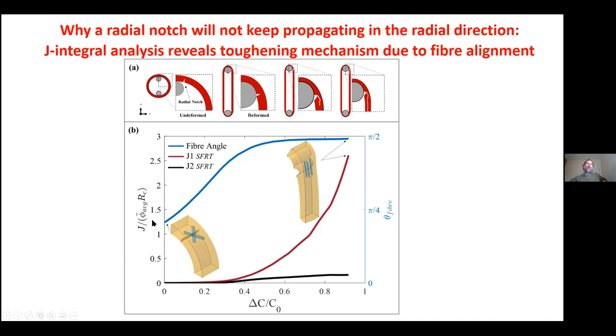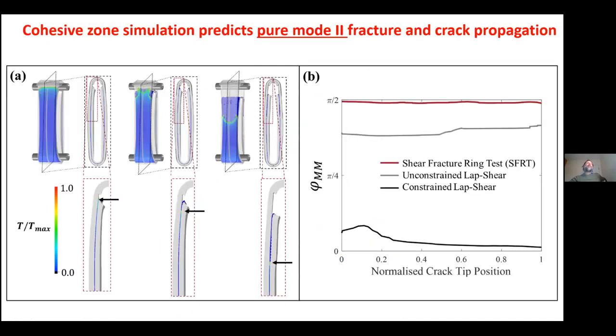If we look at the J integral, it is very high due to this for radial crack propagation compared to propagation in the shear direction. The J integral is like a measure of the energy at fracture, in a sense. So this is what our finite element model predicts.